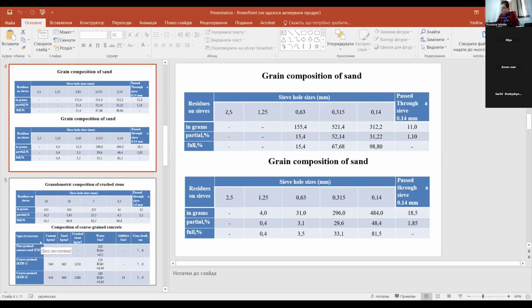Experimental research methodology. To study the low cycle fatigue of concrete more thoroughly, samples made of heavy concrete using traditional aggregates, two types of coarse-grained concretes, and samples made of fine-grained concrete with sand as the only aggregate were fabricated and tested in the research laboratory. The concrete samples were made with slag portland cement. For sand concrete, the aggregate used was quartz sand with a fineness modulus of 1.8 to 2.2. The sand was thoroughly washed of clay and sieved in portions and dried.